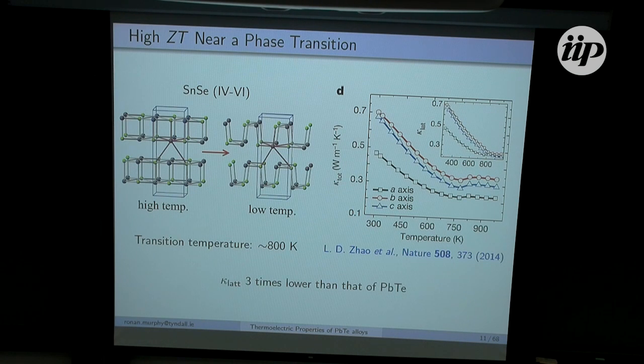Now, from this paper, if we take a look at the thermal conductivity of tin selenide, you see that it's extraordinarily low. It's about three times lower than that of lead telluride. And interestingly, if we take a look around the phase transition, we can see that there's an ever so slight kink in the thermal conductivity near that point. So now again, let's take a look at the electronic properties of tin selenide and see how they're affected.